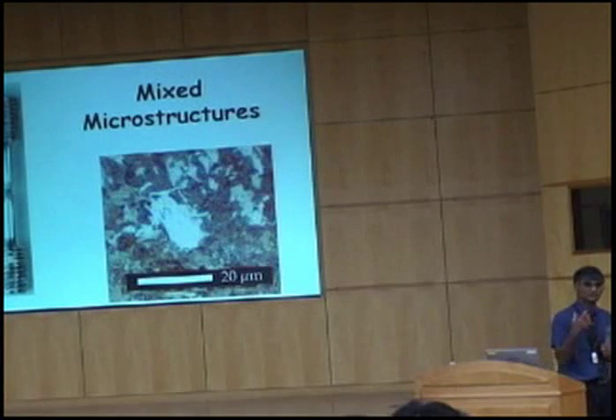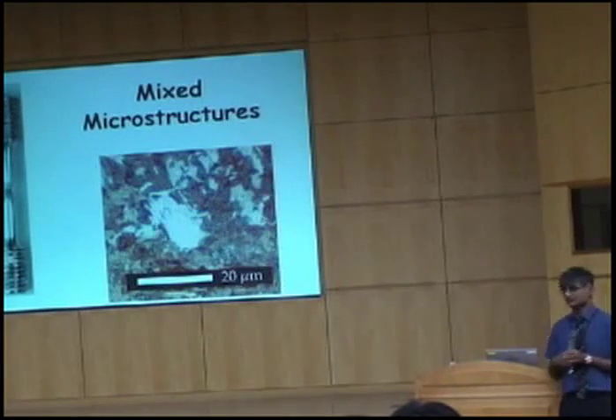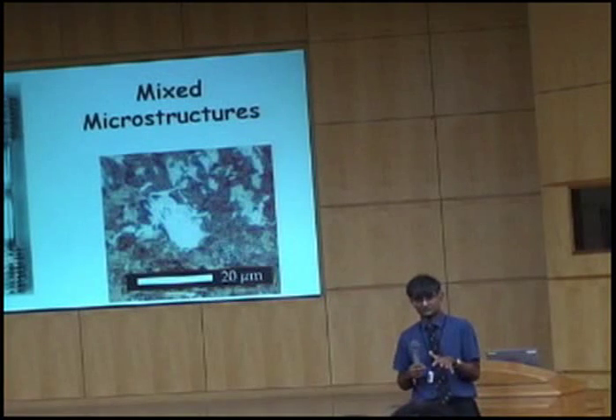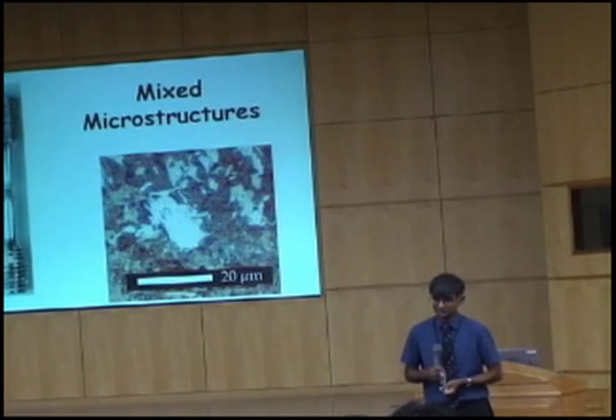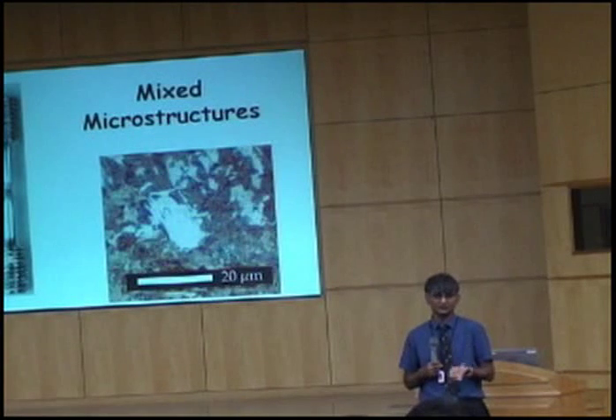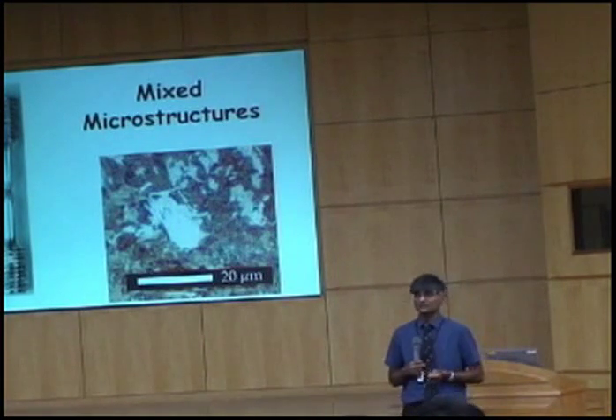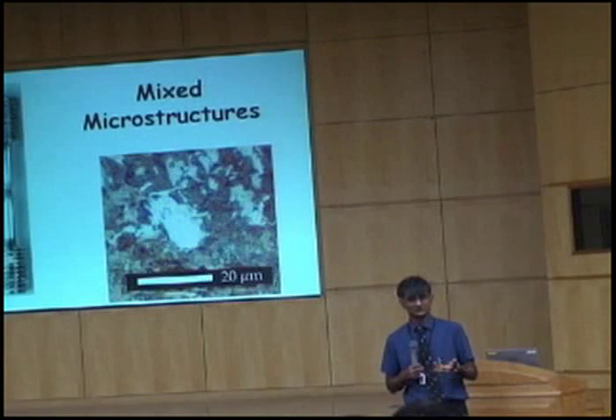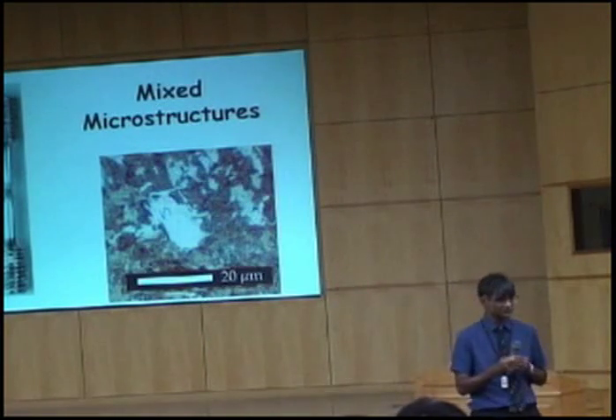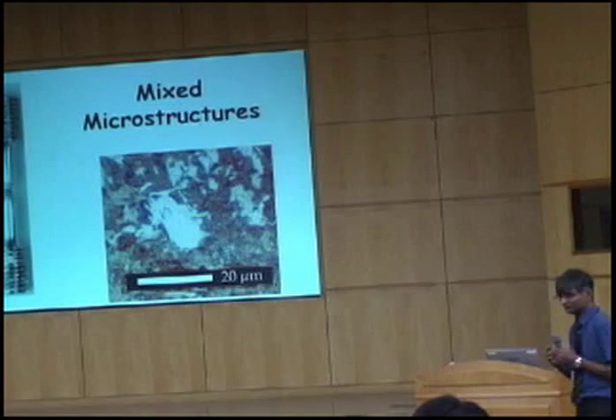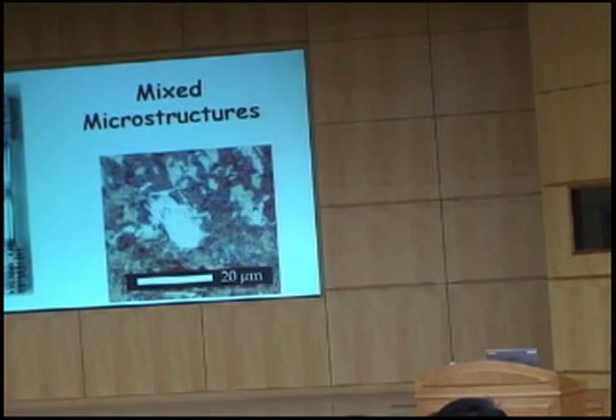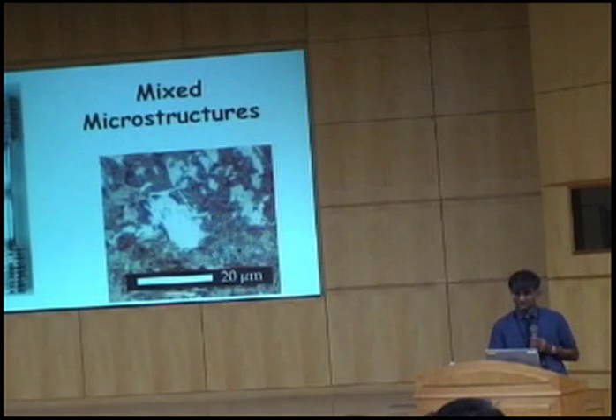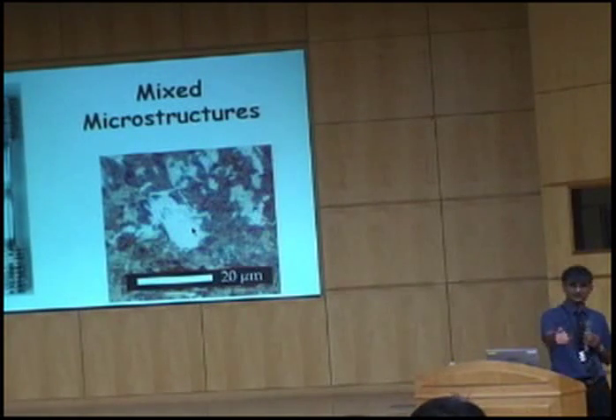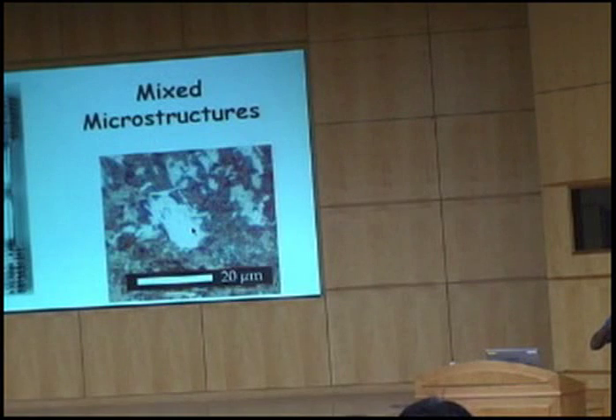Now, all of this theory that I've just explained, I've explained for a single phase. That means you've got a certain dislocation density inside a grain, you've got a certain grain size, and so on. But in steels, we frequently don't have a single phase. We have a mixed microstructure. And the normal way of dealing with a mixed microstructure is to calculate the strength, for example, of bainite and the strength of martensite, and then add them up by multiplying them by the volume fractions of the phases and simply add them up. Okay, let's see if that is justified.